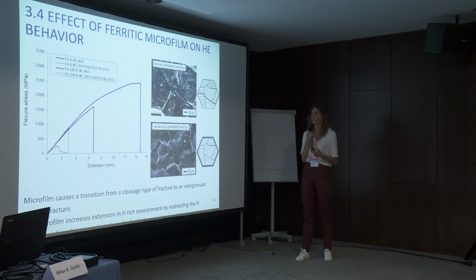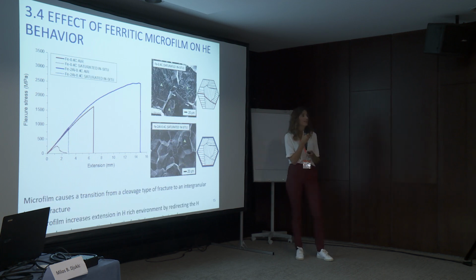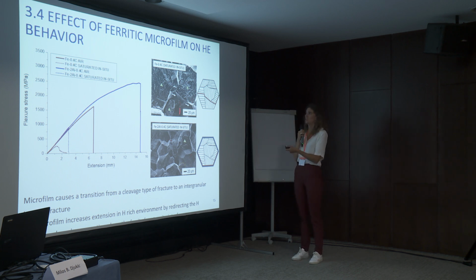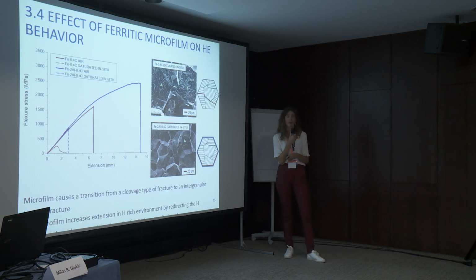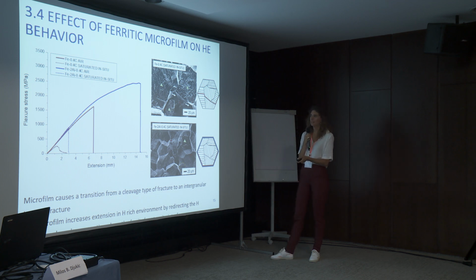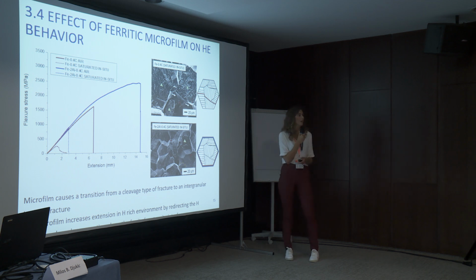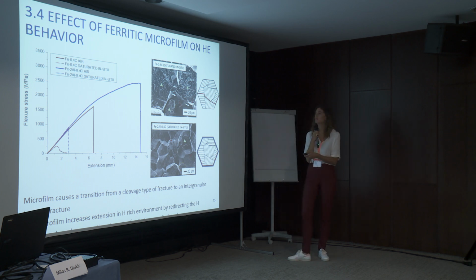And then it's of course interesting what happens when we also add hydrogen. Well, as I showed before, without aluminium, we really have this transition to a cleavage type of fracture by the HEDE mechanism. But if we add aluminium, you can see we can sustain much larger extension values than without aluminium. And we can also see a completely different fracture behavior. So with this ferritic microfilm, we really have a transition with hydrogen to an intergranular fracture path.